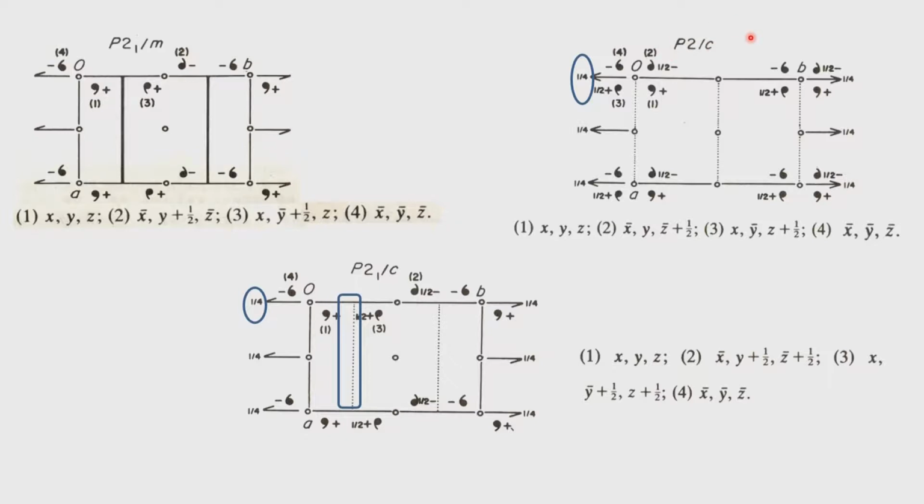So, by just looking at this, we can anticipate how many equivalent points come. This is in general, in the unit cell, and it also tells us about the way in which this operation takes place. We have already seen that whenever there is a translational component associated with the symmetry operation, that particular symmetry, the two-fold, will have to move by 1/4 from the origin in order to accommodate the requirement of 2 by M symmetry, which is the presence of the center of symmetry.